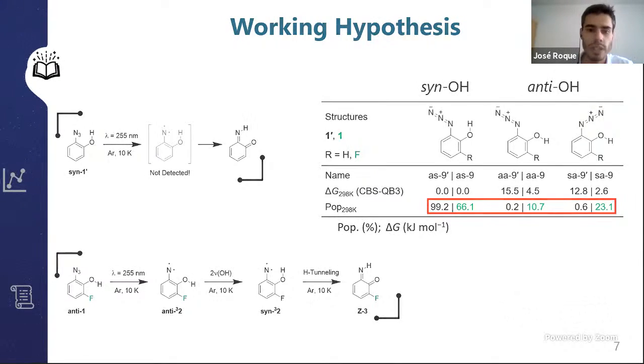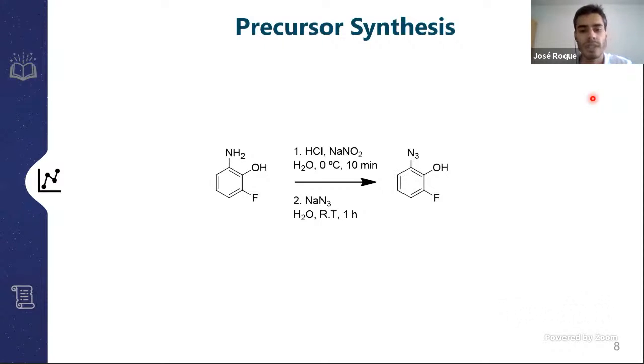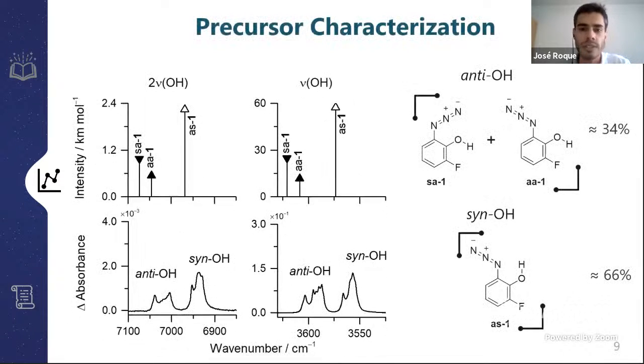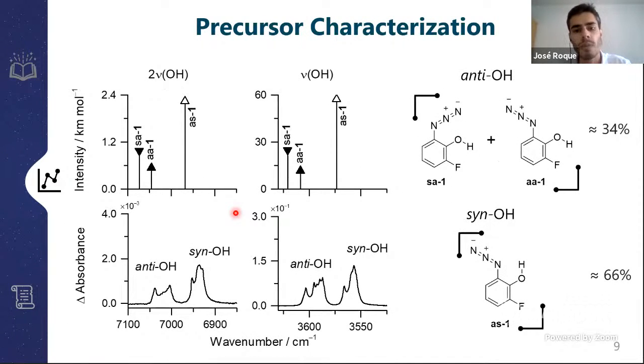And indeed, we advanced with it, and we began our studies by synthesizing this azide, by treating an aniline derivative with sodium nitrite and sodium azide. And after the synthesis, we characterized this molecule by stationary infrared spectroscopy, by preparing a matrix with our substance and nitrogen gas at 10 Kelvin. And in this slide, you can see